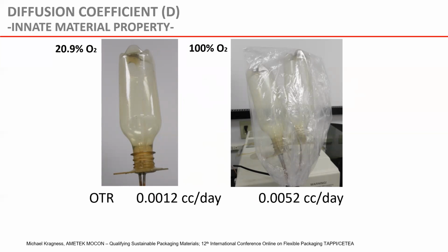And then the test comes to equilibrium, and you can see the difference in the transmission rates. That makes sense because 100 divided by 20.9 is about 4.8. So the difference in the transmission rate should be about 4.8 or so, being consistent with the concentration that we're challenging the bottle with. But what's interesting about the diffusion coefficient is, do you think that it took more time or less time for the 100% oxygen test to come to equilibrium versus the 20.9% oxygen test?